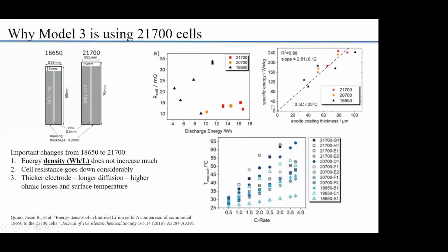The specific energy is also dependent on the anode coating thickness. But as you see, the 18650s and 21700s are on par. They go hand in hand. So by increasing the coating thickness, there's no appreciable increase in specific energy. In fact, if you make the electrodes very thick, it takes longer and it's more difficult for lithium to diffuse, and then you increase the ohmic losses.